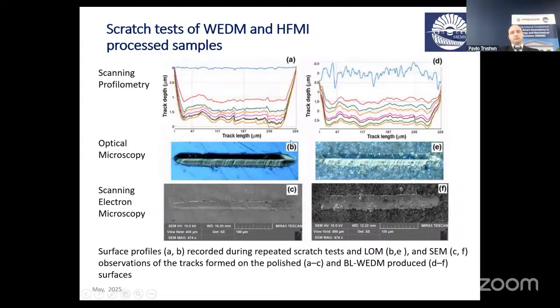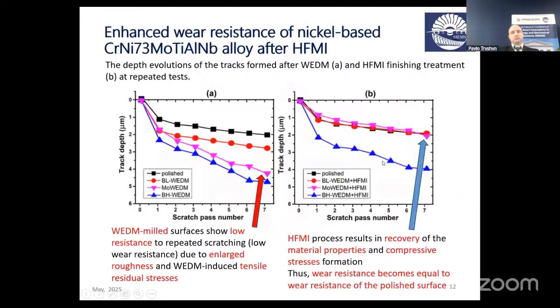Here we can see the polished surface and the surface after the light EDM process. The results are here. On the left, we see that in comparison with the polished material, the depth of the scratch tracks is much higher after EDM, indicating worse wear resistance. However, after finishing deformation treatment, we can restore the wear resistance by equalizing the depth of the polished and EDM processed materials for the light and middle regimes. However, the hard regime needs a more intensive deformation process, and the regime should be determined further.